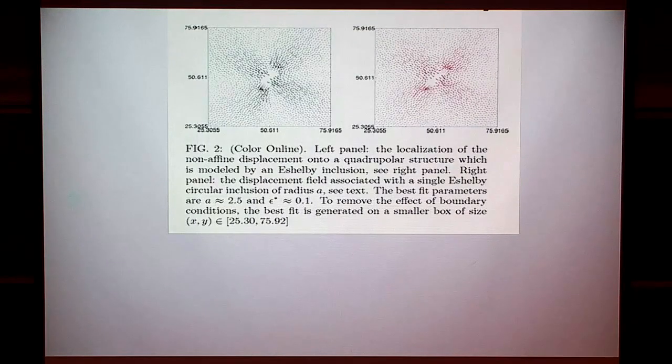Okay, but now what I'm going to use is the fact, already raised by a few people, that these eigenfunctions are also isomorphous to Eshelby inclusions. As you know, Eshelby in the 50s solved a seemingly irrelevant problem: you take an elastic material, carve a hole, take the material out, stretch it into an ellipse, and stick it back, and then you get a displacement field or a stress field that you can find analytically.